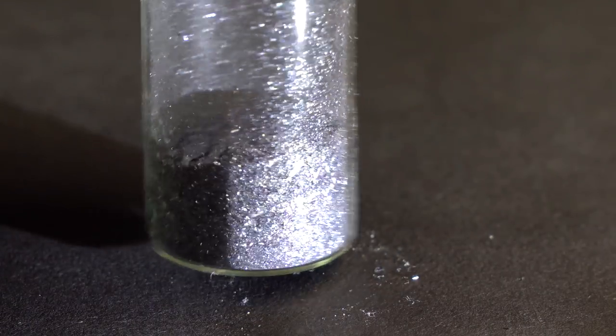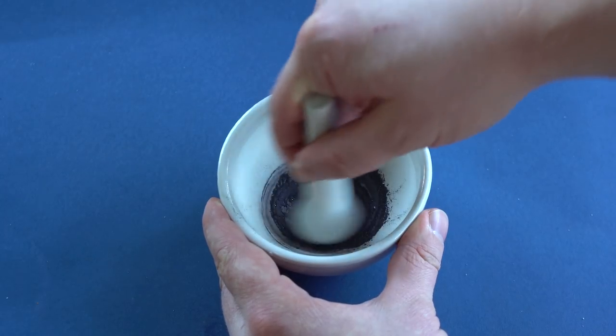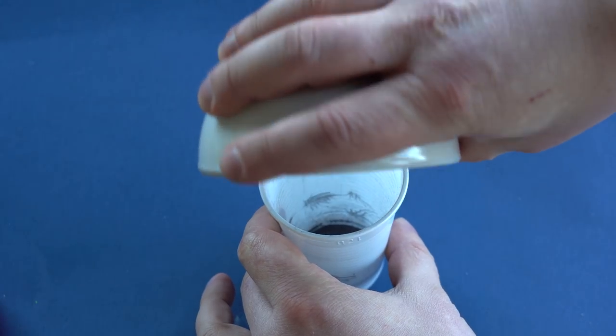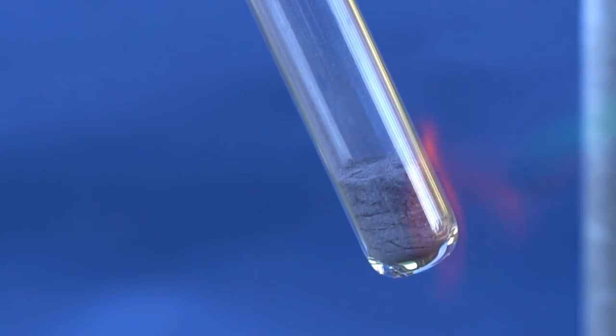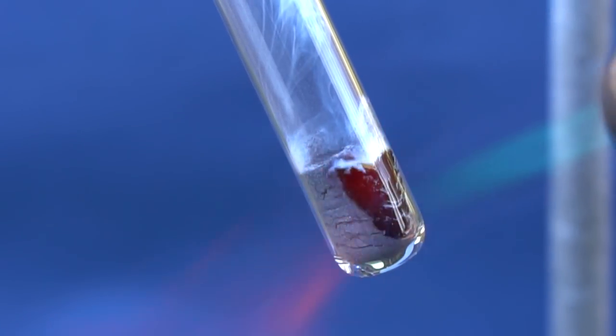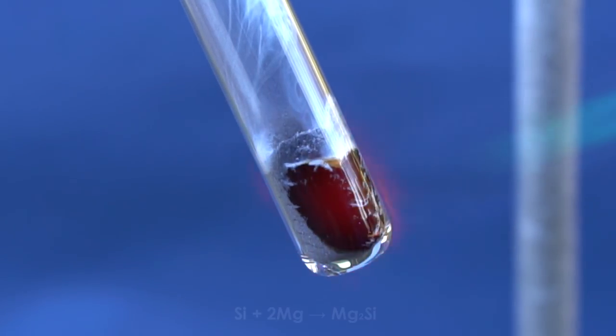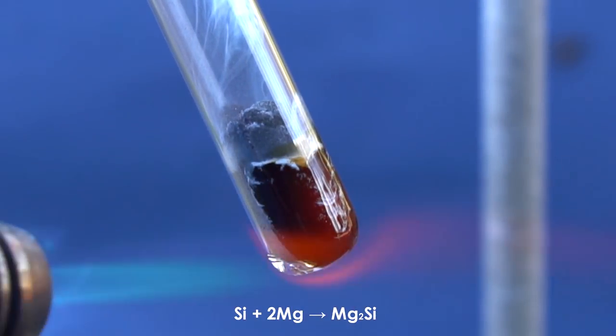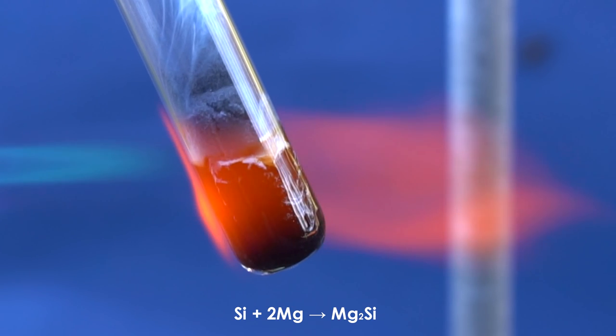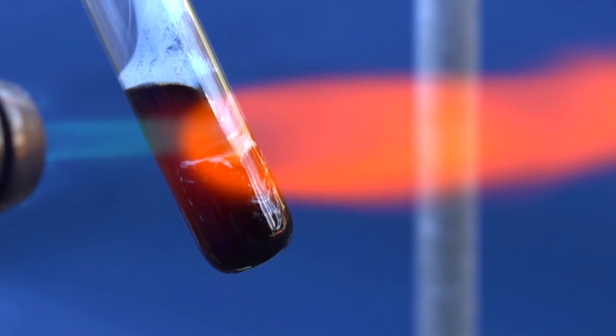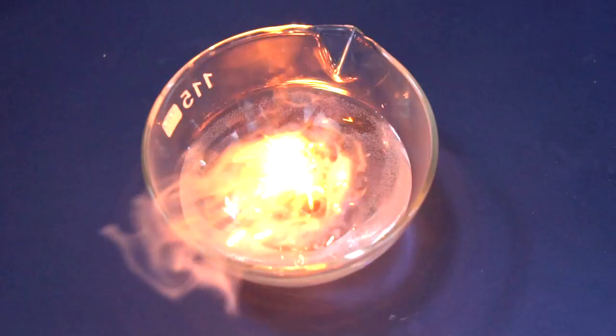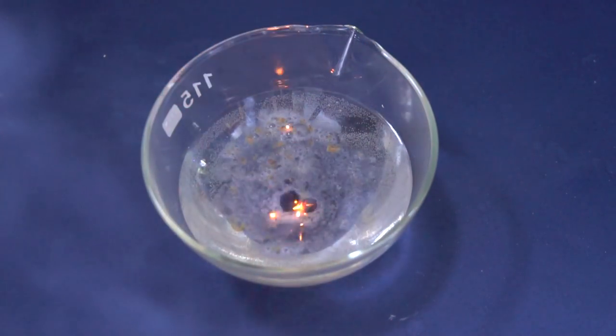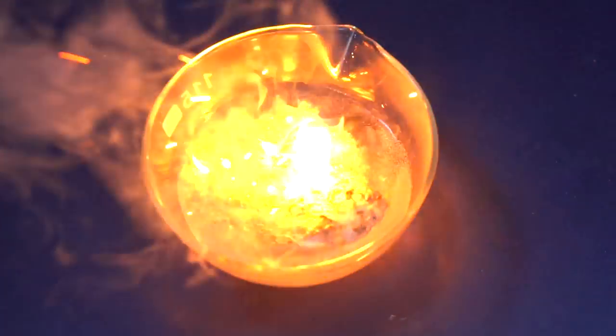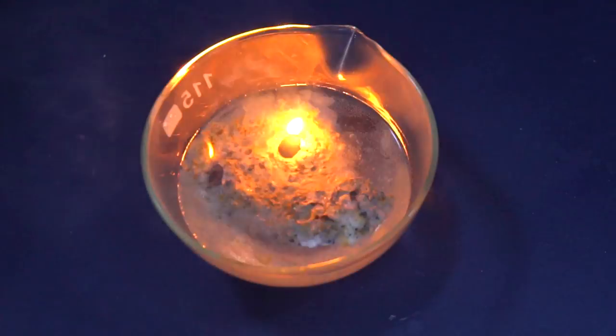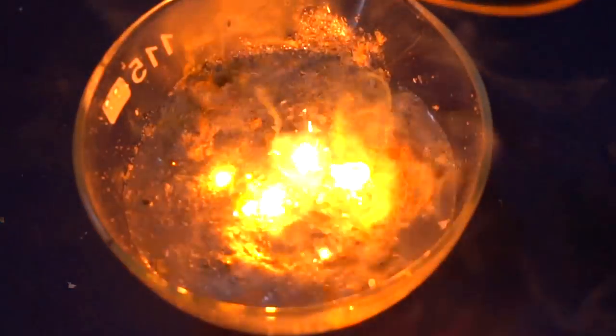There is yet another way to purify the obtained silicon. I'm using a silicon powder and grind it even more in a mortar. Now I'm mixing it with magnesium powder. Then I'm going to heat up this mixture in a test tube. The silicon begins to react with magnesium, producing magnesium silicide of higher quality than the reaction between magnesium and sand. If we add the obtained chemical to a 10% sulfuric acid solution, the reaction will produce quite a large amount of pyrophoric gas silane and even more other silicon hydrogen compounds.